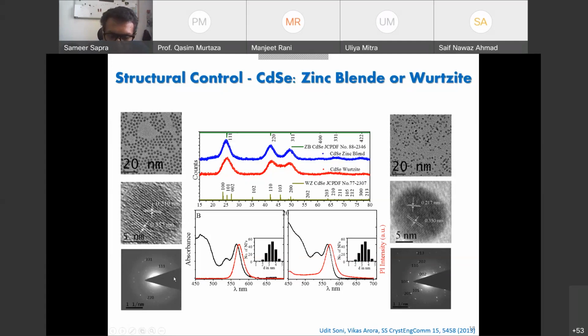So you could do the electron diffraction, you can see all these X-ray diffraction peaks. Of course, they are broad, and I believe a lot of you understand what the Scherrer broadening is. You can estimate the crystallite size from there. The only difference that you'll see is this 103 peak appearing slightly in CdSe wurtzite and not appearing in zinc blende. But as you make the particle size bigger and bigger, you start to see three peaks appearing here and only one over there, and these peaks get narrower as the particle grows.